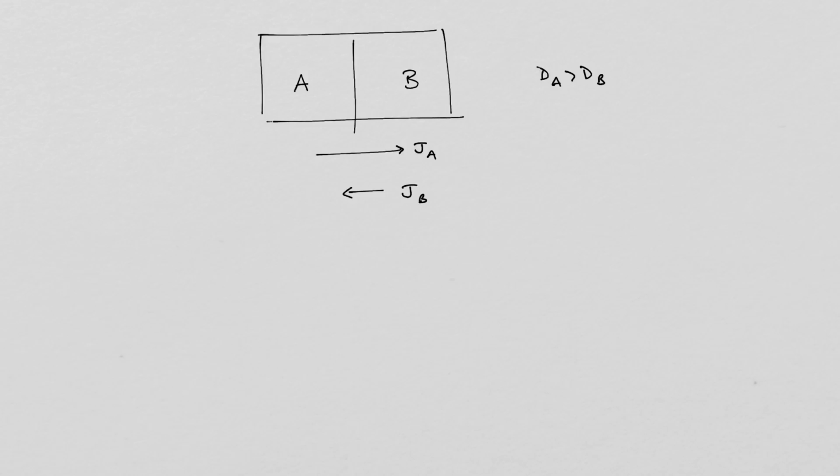I'm assuming the same crystal structure as we have all the way through. So atoms are going to mix within the same structure. They've got the same lattice, they sit on the same sites. So A and B compete for the same sites, which is what we always have before. Yeah, so it's not interstitial. We can assume here A and B are similar size, so the energy to put a B atom into an interstitial site of an A crystal is just too high to contemplate. It's not going to happen.